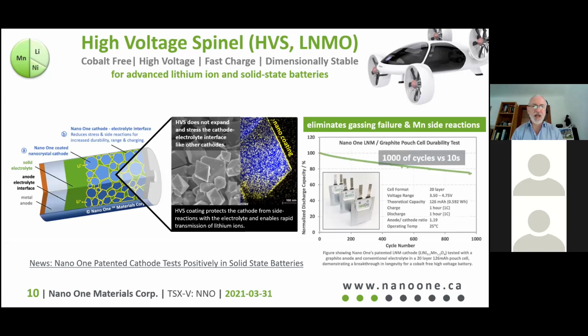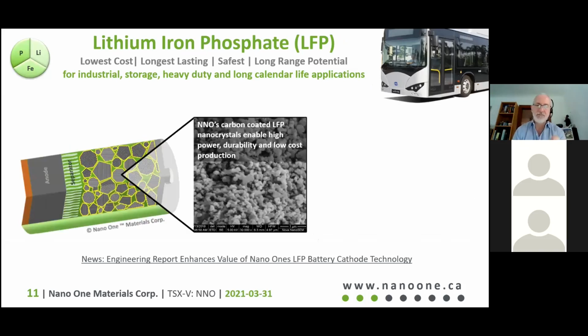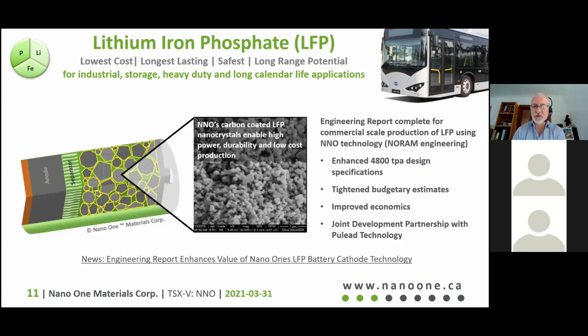Just to complete the set, we also make lithium iron phosphate using a similar one-pot philosophy. The chemistry is slightly different because this is a phosphate, not an oxide, but we're able to make it in the same way and produce nanocrystalline lithium iron phosphate crystals. Here the coating is not the same. It's a carbon coating, added in the same way in the one-pot process without any subsequent carbon coating steps. We are in the process of scaling this up with Pulead, our joint development agreement with Pulead in China.